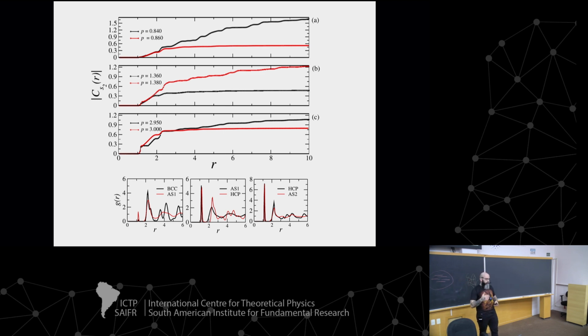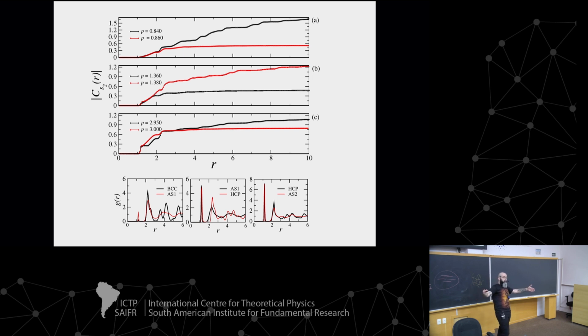So if you have a well-defined structure as in a crystal, this has to increase, as this black line here. But if you have a disordered state, as a fluid or an amorphous phase, you reach a plateau, like this one here. So this allows us to see whether our system is a solid phase, well-structured, with long-range structuring, or whether we have some kind of short-range structuring, as in an amorphous phase.